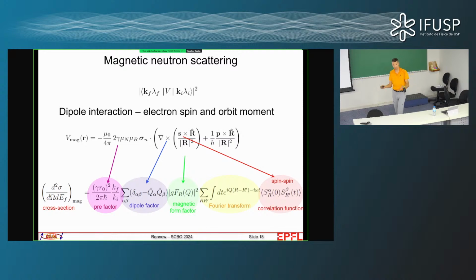In the sample we have electrons. These electrons carry a spin, and they carry an orbital angular momentum. And actually, the neutron itself carries a spin, so we have a dipole-dipole interaction. This looks like a little bit of an ugly interaction term, but magic happens, and once I Fourier transform this, it becomes very simple. So what I end up with, the cross-section, which is the intensity I measure in my neutron experiment, has some fundamental prefactors that I know all about. It has a dipole factor, which is very simple to calculate.